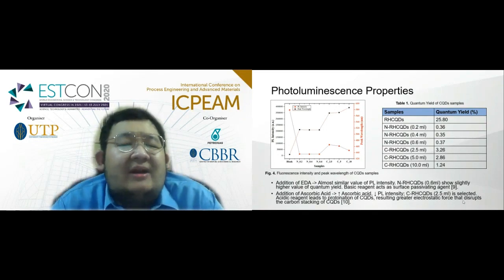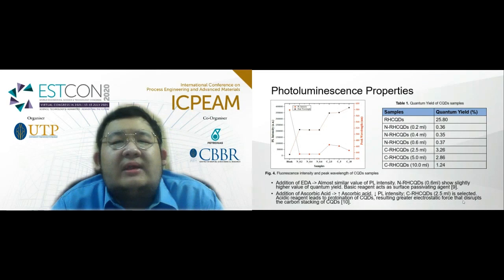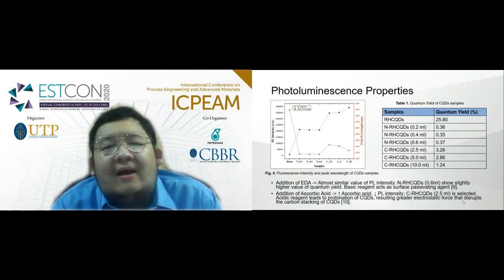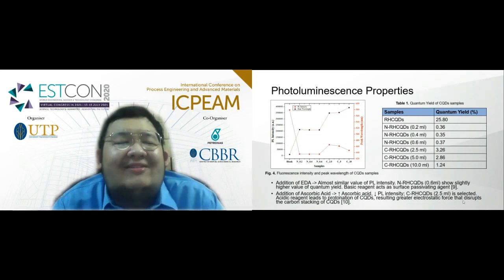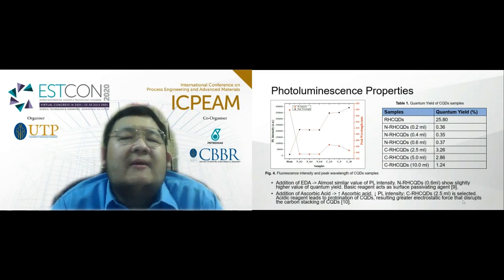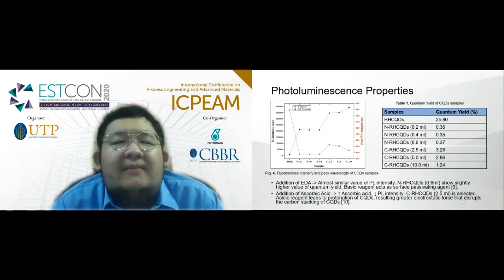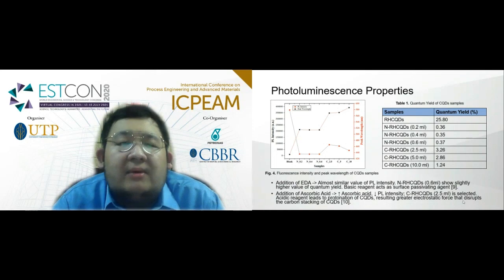The acidic reagent leads to protonation in the CQD, which results in a very high electrostatic force that disrupts the carbon stacking in CQD. That leads to the drop in PL intensity and also the drop in the quantum yield.